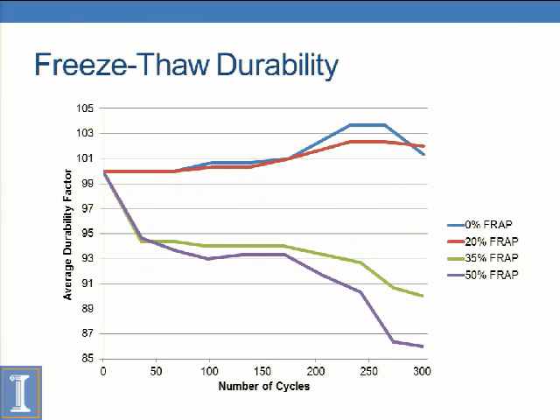And just here's the freeze-thaw durability over time. You can see that our 50% mix here at the bottom eventually had the lowest durability, but still pretty good. And you can see that the 20 and 0 were both pretty good.